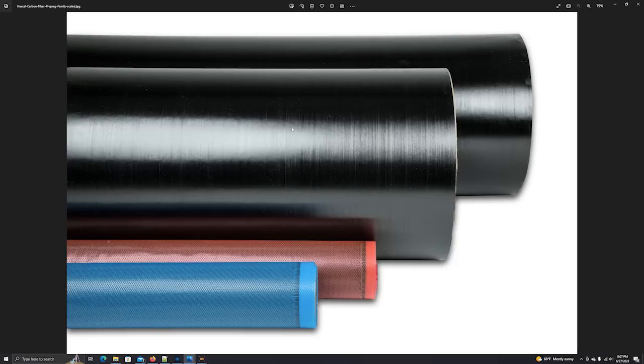Now, what you see on the screen here is what is called a pre-impregnated fabric. And when the carbon fiber is manufactured, after it's been created into a carbon fiber, they go through and they very carefully meter out an exact amount of resin onto the fabric. And this is done by an automated machine process. So your exact resin is exactly the same across all of the prepregs. Now, what they do is they partially cure these prepregs, and then they store them in a freezer.